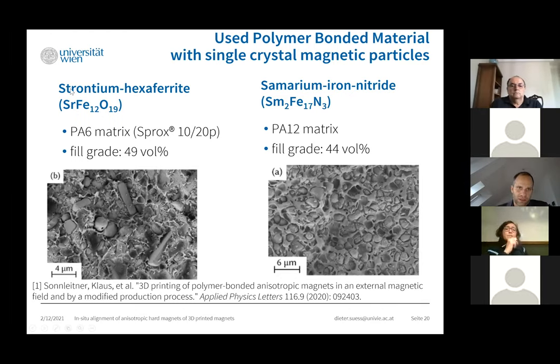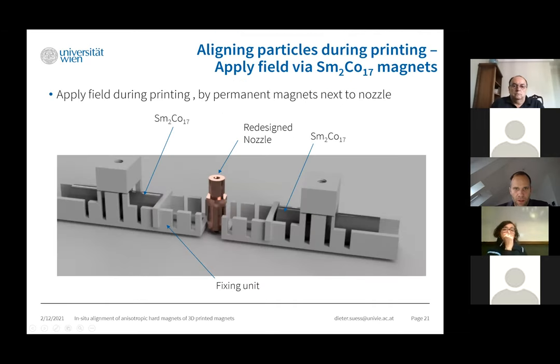So these are now the two materials that we tried out successfully. One was a strontium hexaferrite embedded in a PA6 matrix with a fill grade of about 49 volume percent. And the second one is samarium iron nitride embedded in a PA12 matrix with a fill grade of 44 volume percent. You see these two different structures have also different shapes. Here we get quite elongated particles, whereas here for the samarium iron nitride, we have more spherical structures.